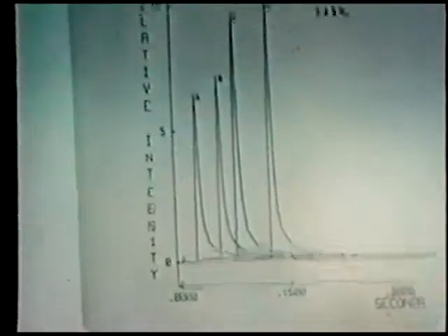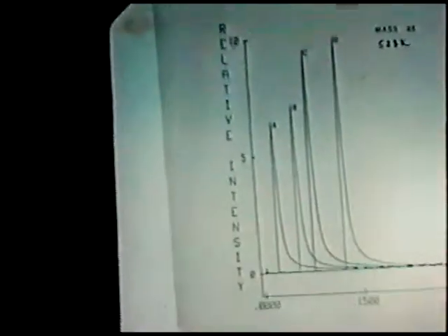Now, before I show you, let me show you one effect here that's interesting and which we don't completely understand at this point. This is a pulse probe experiment where oxygen has been pulsed in to load up the catalyst, and then ethylene follows at varying times, and the ethylene pulses are equal in size. And here we have the amount of ethylene oxide formed at 523 Kelvin as a function of the pulse delay. What's interesting about this is that for very short pulse intervals, there seems to be a process here which retards the formation of ethylene oxide.